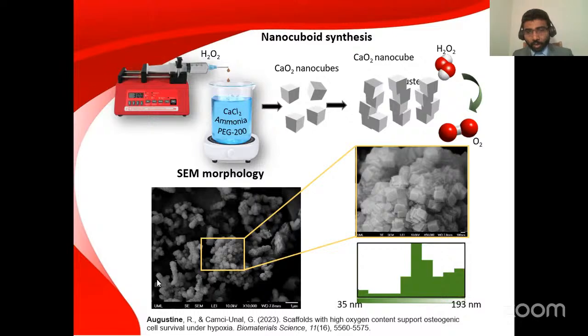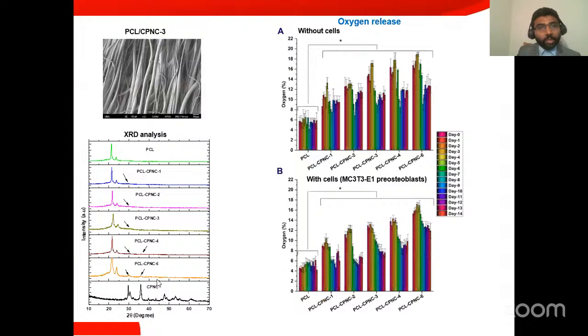It was like 35 to 200 nanometer in size. Then when we incorporated it in electrospun scaffolds, the fiber structure was like that. We developed aligned fibers using a rotating mandrel. Then we characterized it using various techniques, which I'm not showing all of. We also conducted mechanical studies, so many studies. Then we performed oxygen release studies without cells and with the cells, pre-osteoblast cells.